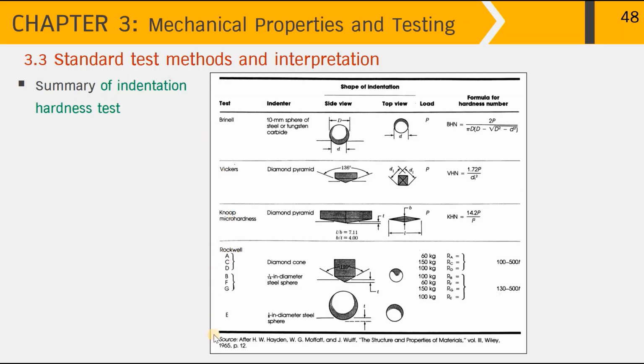And the Rockwell hardness test is different, by measuring the depth of the indentation. But actually there are a range of scales. The first group shows the scales that apply the diamond cone indenter, which are HRA, HRC, and HRD, by applying different levels of load of 60 kg force, 150, and 100 to give different Rockwell hardness scales. And next, we use the steel ball to give HRB, HRF, and HRG by applying different levels of load, for example.